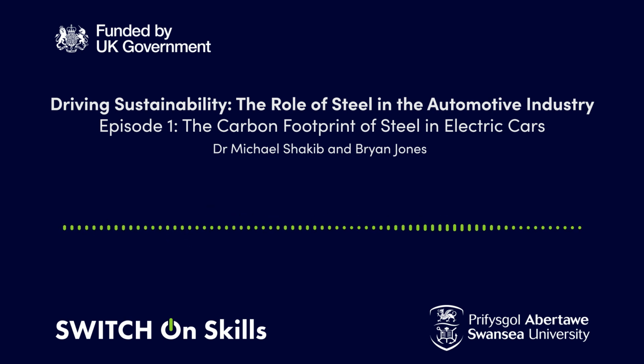Yeah. So a dual phase steel will incorporate a high level of ferrite. Say you're developing a DP600 grade of steel, that's a dual phase steel with a strength of 600 megapascals plus and a small amount of martensite. So the ferrite gives you the formability, and the martensite gives you this resistance to formability, if you like, which increases the strength of the steel. So if you've got a DP600, you typically have 10 to, say, 20% martensite. For a DP1000, you'll have, say, 80% martensite and 20% ferrite.